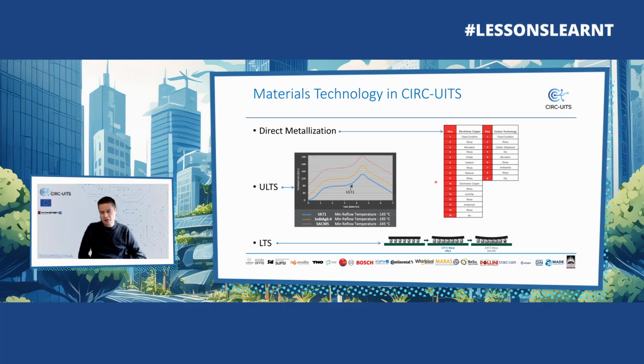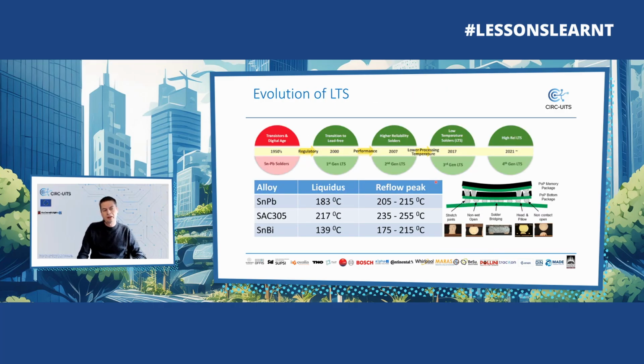Low temp solder was introduced over 20 years ago. So next year will be 20 years ago that there was a ban on the use of lead for soldering in electronics. And you can see here the tin lead solder liquidus. So this is the melting temperature of the alloy at 183 degrees C. That meant we had a soldering range between 205 and 215 degrees C for soldering.